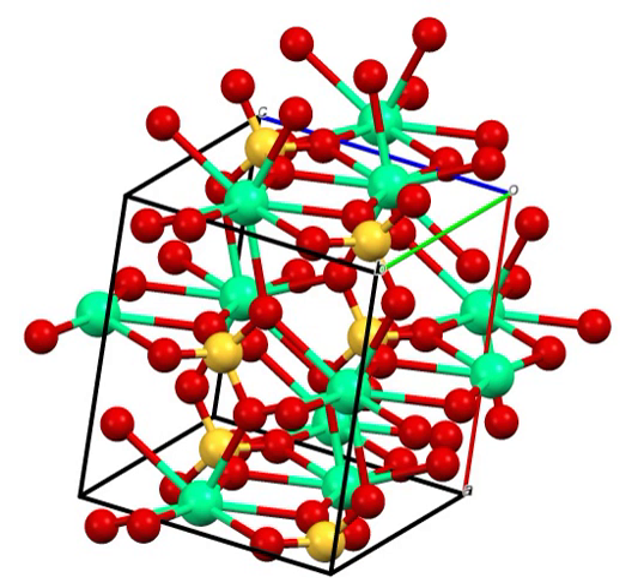In the production of phosphoric acid from phosphate rock, calcium phosphate is treated with sulfuric acid and calcium sulfate precipitates. In the production of hydrogen fluoride, calcium fluoride is treated with sulfuric acid, precipitating calcium sulfate. In the refining of zinc, solutions of zinc sulfate are treated with lime to co-precipitate heavy metals such as barium. Calcium sulfate can also be recovered and reused from scrap drywall at construction sites. These precipitation processes tend to concentrate radioactive elements in the calcium sulfate product.